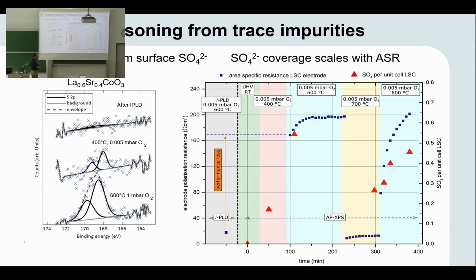And very recently, in collaboration with Christoph Ramechan, we could find out that trace amounts of sulfur are the actual reason for this degradation. So for almost magical reason, in our PLD chamber, no sulfur traces seem to be present in the atmosphere. So we have very high kinetics, and when we investigate the pristine sample, we find no sulfur at all. And once we heat the sample in even very, very low partial pressures of oxygen, so 10 to minus 3 millibar is sufficient to get a significant amount of sulfur, which increases with annealing time, and also the degradation rate of the electrode is very fast.